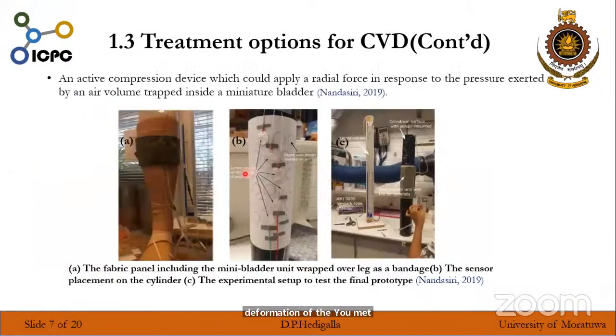Hence, novel research has been carried out to develop an active compression device which could apply a radial force in response to the pressure exerted by the air volume trapped inside the mini bladder. And they have shown that the developed active compression device could apply a uniform pressure around the limb circumference. It was done by placing AMI air pack sensors around the limb circumference such that they coincide with the mini bladders, and then measuring the pressure values. And they have shown that all the pressure values are the same.